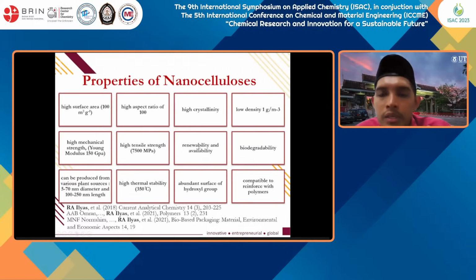This sums up the properties of why we are using nanocellulose instead of other nanoparticles or nanofibers. It has a high surface area, high aspect ratio, high crystallinity up to 90%, low density, biodegradability, renewability, and availability. It has high tensile strength up to 7.5 gigapascal, high mechanical strength, Young's modulus up to 150 gigapascal, and it can be produced from various types of plants.